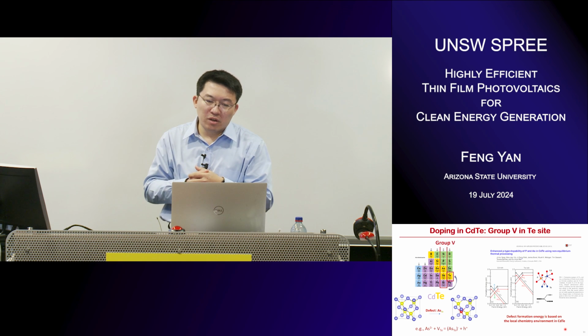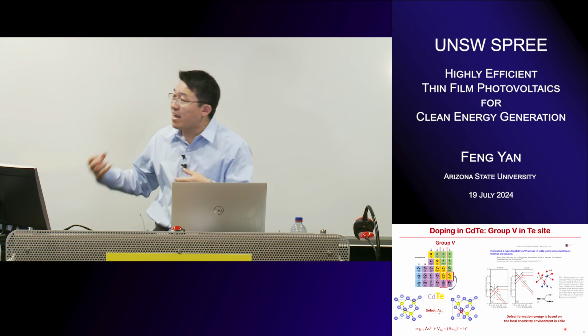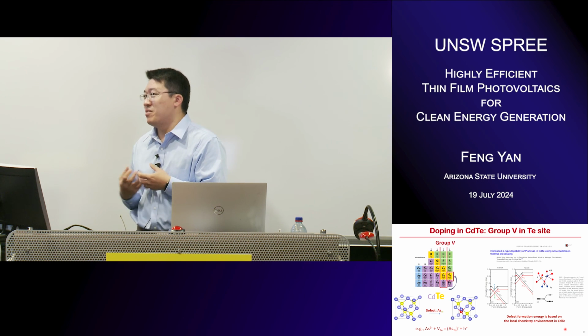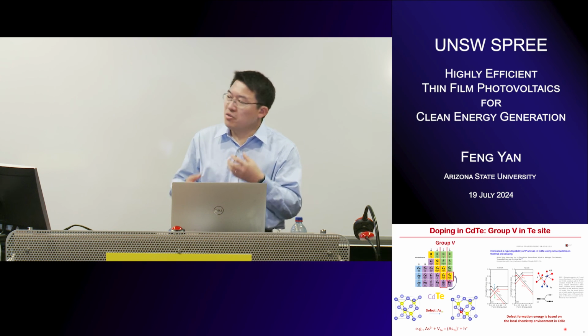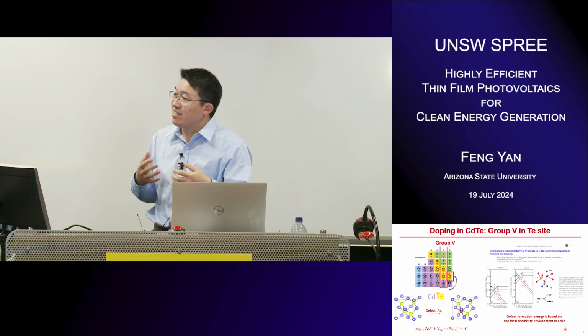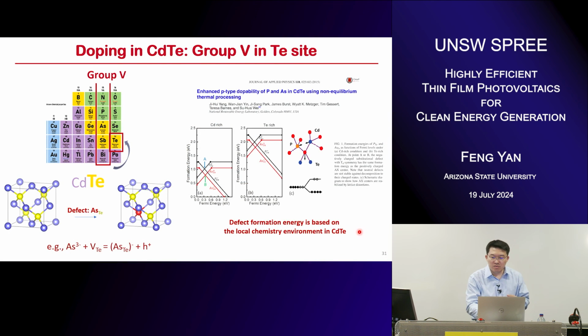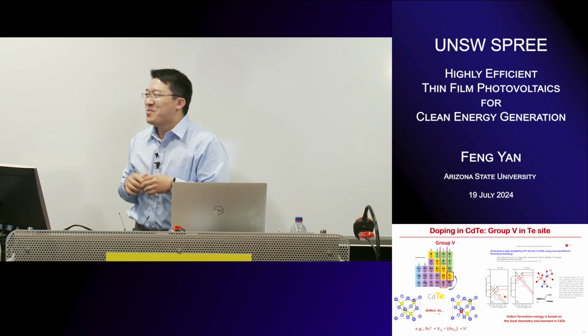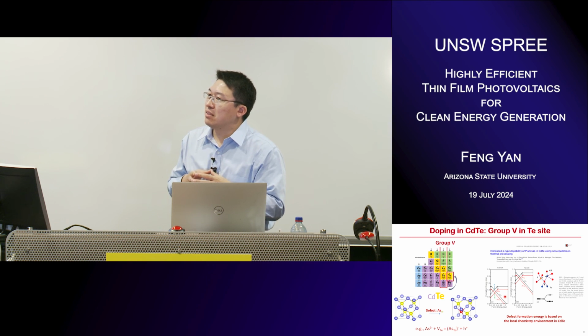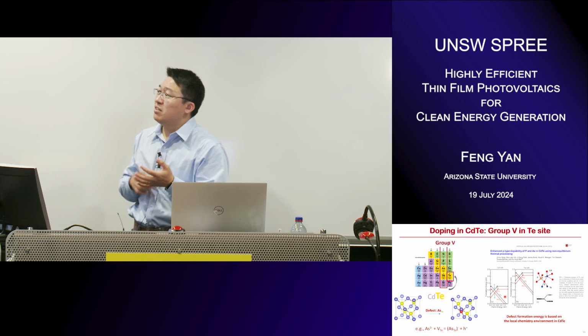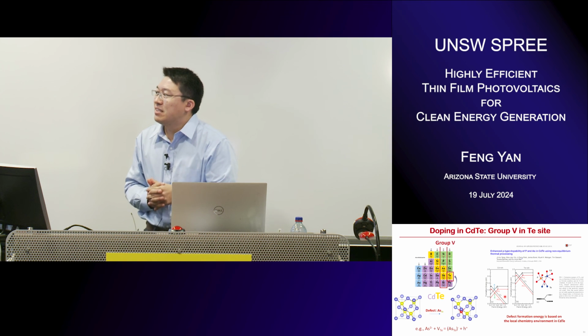But overall, it's not only about the element, it also relies on the treatment environment. Yes, exactly, that's another challenge. We need to tune a lot of conditions to get the element where we desire. For example, here is one defect calculation for phosphorus and arsenic. You can see that in cadmium-rich and tellurium-rich conditions, there are different defect formation energies. So we probably need the cadmium-rich condition to drive the element much easier. Overall, it's pretty critical to get precise control of the dopant precursor selection and the process, which need to be combined together. Pretty challenging work.